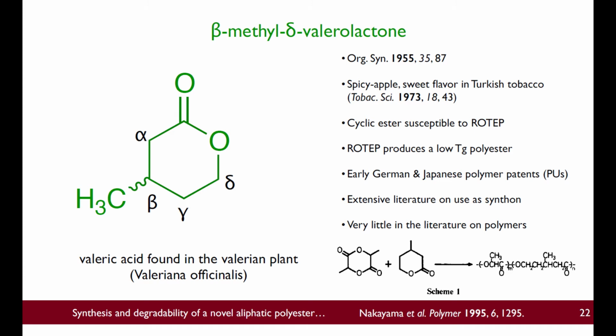Now, why am I interested in this molecule? Well, it also is a cyclic ester, not unlike lactide or menthide. It has this ester unit in this six-membered ring. It has this one methyl group. It turns out to be very important for generating a low glass transition temperature polymer. But what my colleague Kachun Zhang saw was actually this molecule, beta-methyl delta-valerolactone, can come from mevalonate.